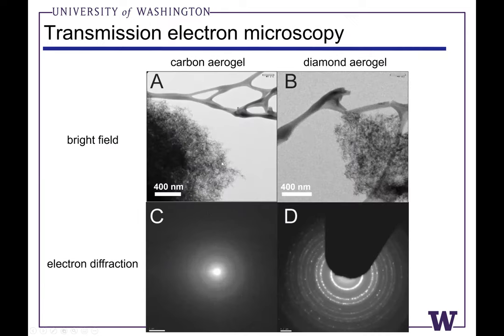We can also take these materials to an electron microscope. This is a carbon aerogel that we've pressurized but not laser heated as a control. We do electron diffraction on this material, and you can see a lack of crystalline diffraction. Basically, we just have amorphous scattering. But if you laser heat the carbon aerogel, you can image the microstructure. You can still see it's very porous. But under electron diffraction, you can start to see these very bright diffraction rings that index to cubic crystalline diamond. So this is additional evidence we have that we've undergone a phase transition, not just the visual light scattering evidence,